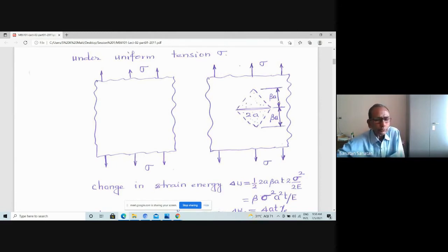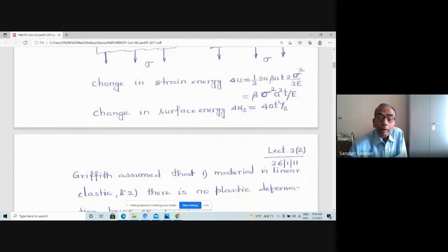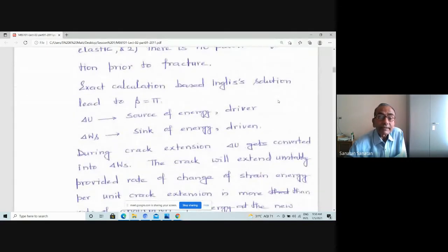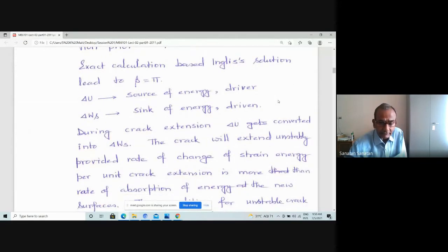So if crack propagation is to take place, your energy supply, that means strain energy availability for crack extension, must be more than the required energy for the surface creation. So he propounded that the rate of release of strain energy is the source of energy, and the rate of absorption of surface energy is the requirement. So the sink of the energy is the surface, and the source of energy is the strain energy. The driver is the source of energy, and the sink is the driven. So the crack propagation process is the conversion from strain energy to surface energy.